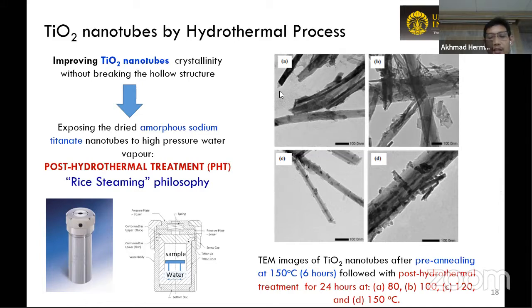That's why we give a pre-annealing treatment at 150 degrees Celsius using a conventional furnace, followed by post-hydrothermal treatment. By applying this, we can see that the crystallinity of the nanotube has increased. There are some small crystallites protruding out from the nanotube structure. This is an indication that the crystallite size of the nanotubes can grow further, but at the same time the nanotube structure can be maintained here. Next slide, please.